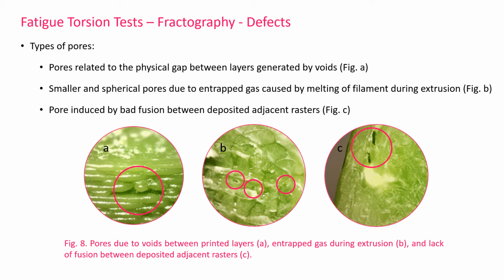From fractography analysis, 3 types of pores were identified. 1. Related to the physical gap between layers generated by voids, shown in Figure 8a. 2. Smaller and spherical due to entrapped gas caused by melting of the filament during extrusion, presented in Figure 8b. And another type of pore due to bad fusion between deposited adjacent rasters, shown in Figure 8c.